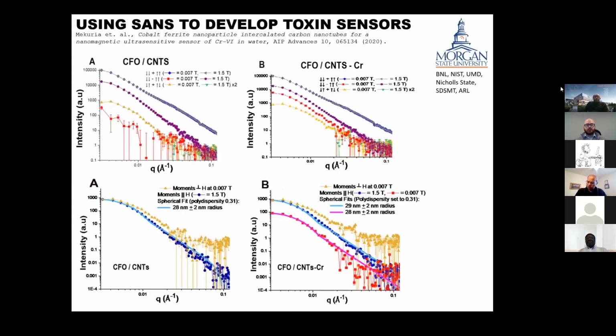What did they find? Now, this slide is going to emphasize the neutron scattering results, but key parts of the research included also using a technique called vibrating sample magnetometry and extended X-ray absorption fine structure, XAFS. The magnetometry showed that whenever you put the chromium into these nanotubes, the magnetization enhances by more than 70%. So it's a pretty significant increase. The XAFS also showed that you get structural changes just based on the fact that the chromium gets incorporated into the nanoparticles.